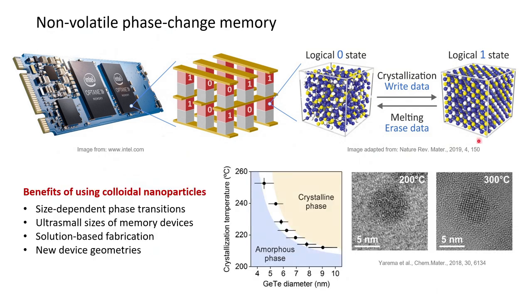So the nanoparticles, with size-dependent crystallization and also size-dependent melting, give us an additional parameter to tune. One may say this is a game changer for phase change memory applications, because if we are entering a sub-10 nanometer size for memory dimensions, then we should care about the size dependence and choose the material wisely. Some more benefits from colloidal nanoparticles are ultra small sizes of memory devices, like a single nanoparticle could be the one, or a very simple and inexpensive solution-based fabrication.